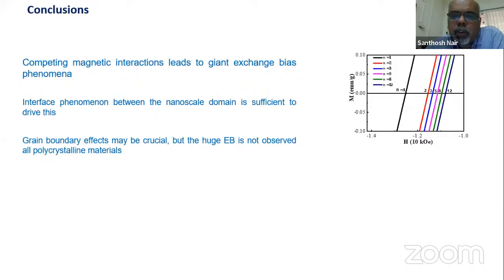So we didn't pursue it further, but rather we modified it. Because in many systems, if you have a manganese-cobalt combination, you end up getting a bit of ferromagnetic interaction. So we just played around with two compositions. Ideally, you should be able to do more compositions, but then it's a messy system. Very interesting. Thank you.